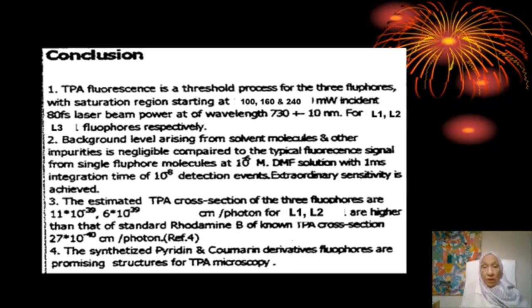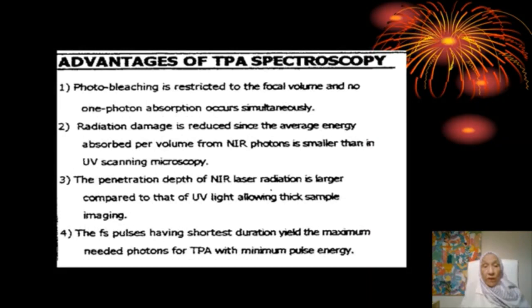The advantages of the two photon absorption spectroscopy: photo bleaching is restricted to the focal volume, and no one photon absorption occurs simultaneously. Second, the radiation damage is reduced since the average energy absorbed per volume from the near-infrared photons is smaller than in the ultraviolet scanning microscope. The penetration depth of the near-infrared laser radiation is larger compared to that of ultraviolet light, allowing thick sample imaging. The femtosecond pulses have shorter duration and yield the maximum needed photons for the two photon absorption with minimum pulse energy.